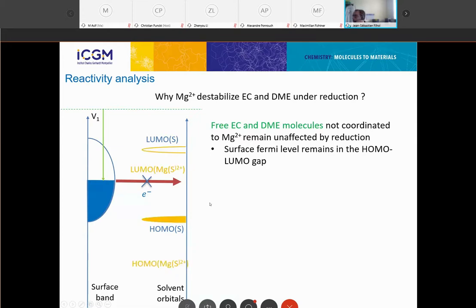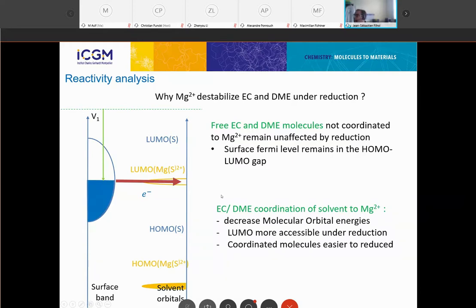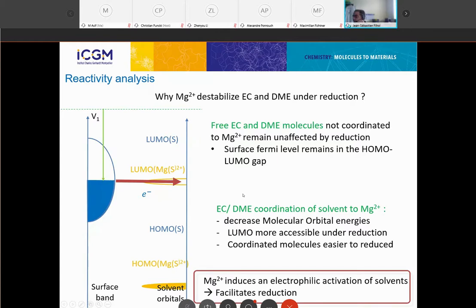But when we coordinate the solvent molecule to magnesium, the effect of magnesium on these molecular orbitals is to shift all these orbitals down. In particular, the LUMO is shifted down, and it can be shifted down into the range of reduction of the surface. So because of the attachment to magnesium, some of the attached solvent molecules are going to be reduced, and this will lead to either dimerization or fragmentation. So one of the problems of the magnesium 2+ is that it creates some kind of activation of the solvent molecule. It's very close to what is observed in organic chemistry, some kind of electrophilic activation that facilitates the solvent molecule reductions. That, in fact, is really the problem. Solvent alone is stable, but when it's coordinated to magnesium, it becomes sensitive to reduction.